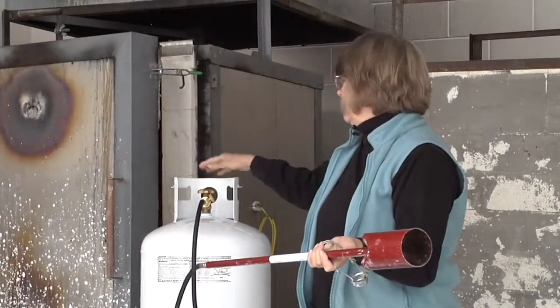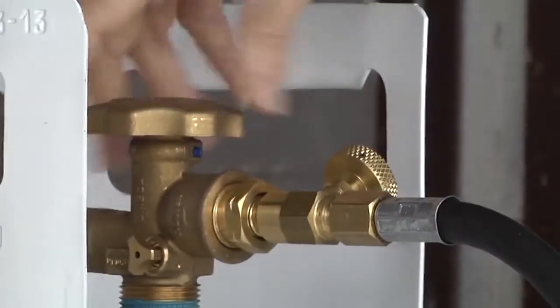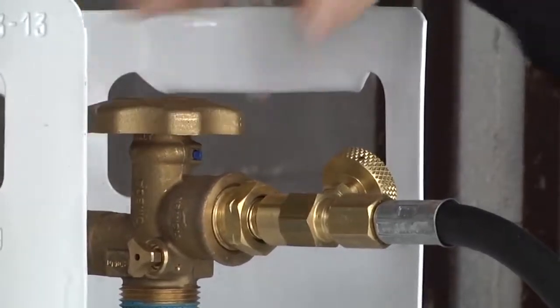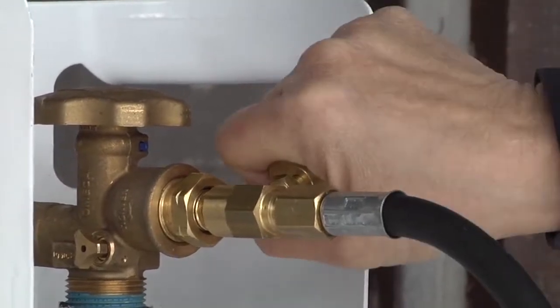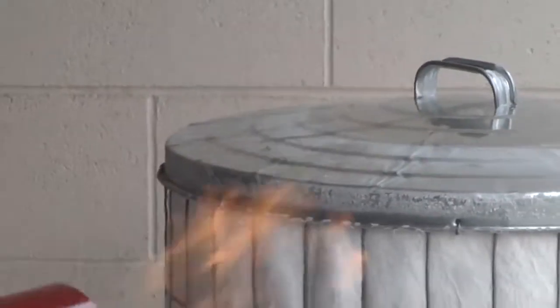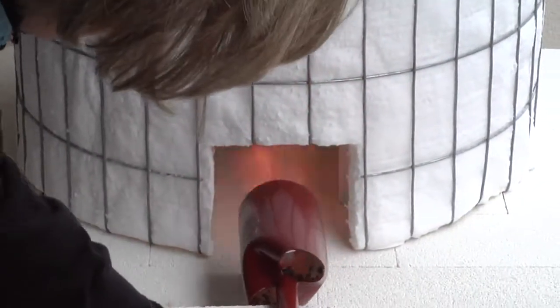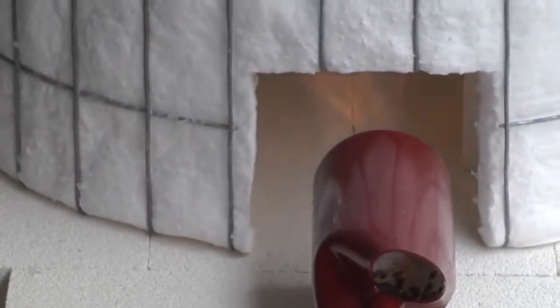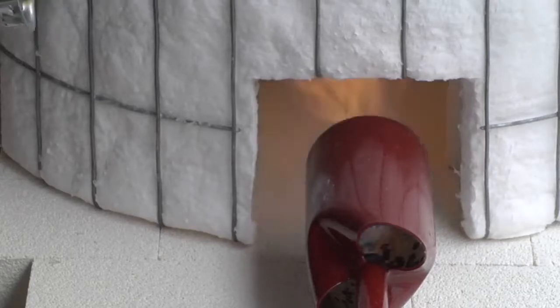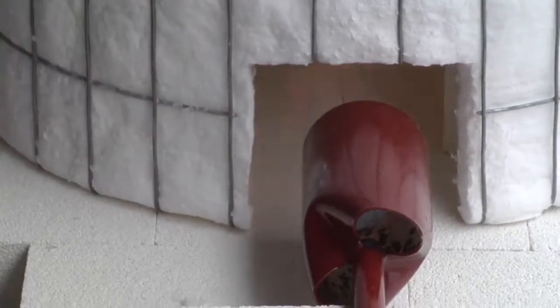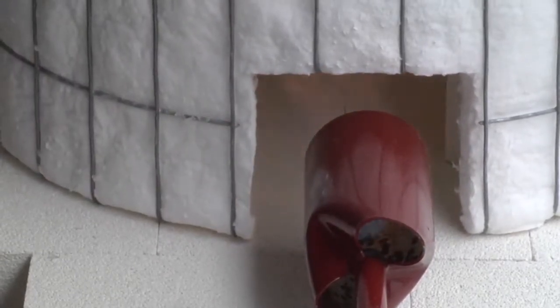Okay, there's 2 valves on the burner and the tank, so I'm going to turn the gas on first at the tank, and then I'm going to turn the burner gas on. Okay, and then I'll adjust it. Okay, and then I'll put it in, line it up for there. Okay, so you want to have a lot of secondary air going into this because it's no blower, it's a natural draft, so you don't want to have it too much in the kiln. It should be outside of the kiln, and it should be able to bring in air around it. So I'm going to just go really slow right now, and then I'll have a pyrometer to watch the temperature.